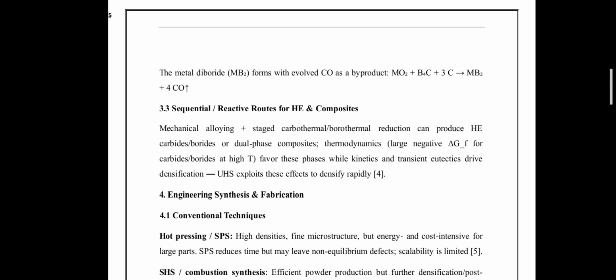Now we will move toward the reactive routes for high entropy composite ultra high temperature ceramics, and reactive and sequential processing. For high entropy ultra high temperature ceramics and multi-phase composites, a simple single-step reduction is often insufficient. Instead, mechanical alloying is used to homogenize multiple metal oxides, followed by staged carbothermal and borothermal reactions. Thermodynamically, carbides and borides are strongly favored at high temperature due to their large negative Gibbs free energy of formation.